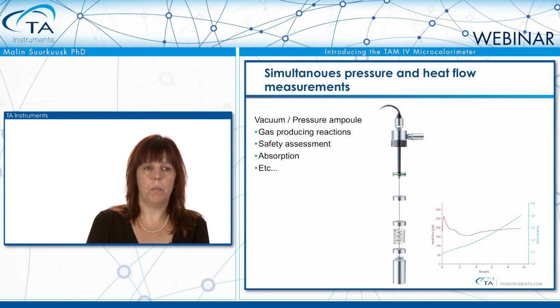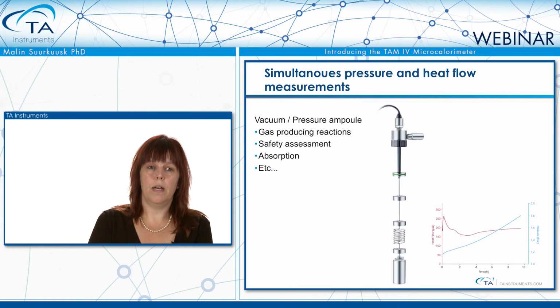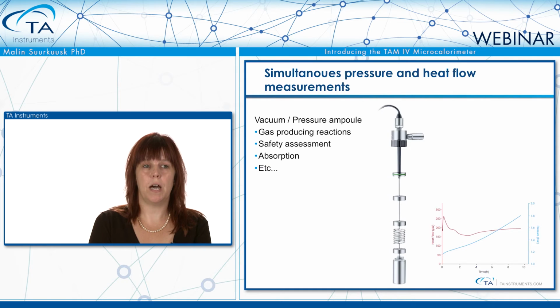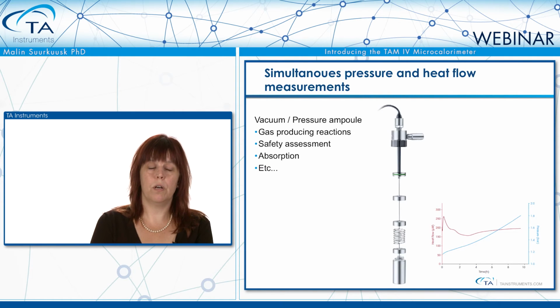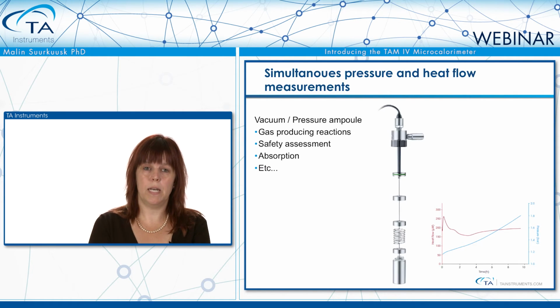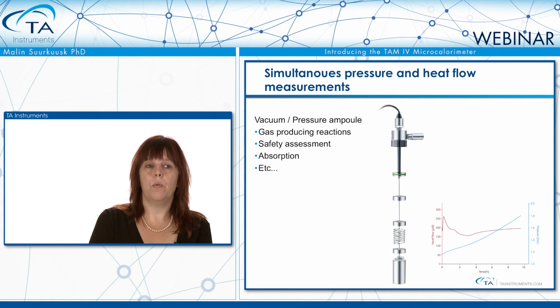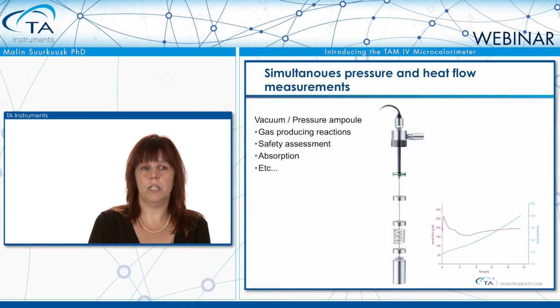In this example, we have followed the simultaneous increase in pressure at the same time as the heat flow. The red curve is the heat flow of an unstable percarbonate, sodium percarbonate sample, and the blue line is the pressure increase while the sodium percarbonate decomposes.